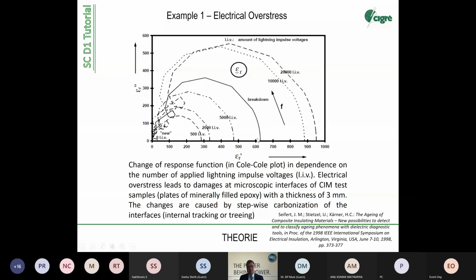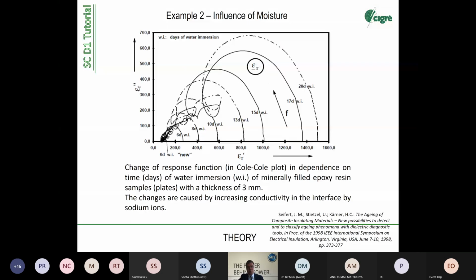Here's a second example. It has investigated the influence of moisture. New sample, if the material comes out of the production machine or out of the laboratory equipment, you have a very low dielectric response. You see the circle, so the Maxwell-Wagner effect. And this sample was water immersed for days in 50-degree hot water. So after 6 days, 8 days, 10 days, 13, 15, 17, 20 days, you see that this Maxwell-Wagner effect is increasing.